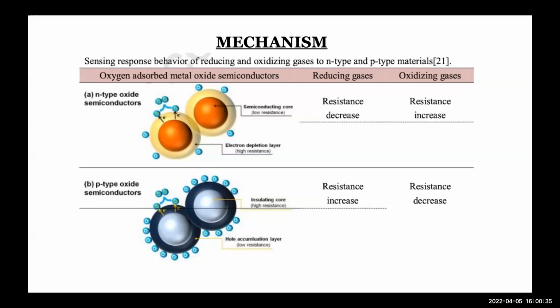So first one is the semiconducting core, which, we all know, has a low resistance. So when oxygen ions are introduced on the surface of the MOS sensor, the resistance increases. And when the targeted gas is introduced on the surface of the MOS, then a reducing gas decreases the resistance and an oxidizing gas increases the resistance.